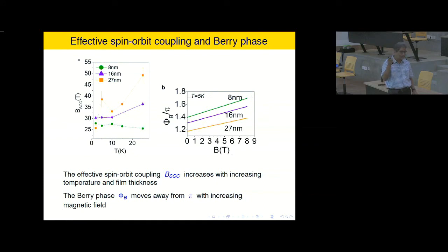Oh, the single crystal, by that I meant a really big crystal, a very, very thick crystal. If you take a very thick single crystal of bismuth selenide, then the surface state penetration depth is 0.8 nanometer. Now in this system, the grain size is typically the thickness. Here the thickness is about 2 to 3 nanometers per grain. And then we are assuming that the two separate grains almost touch each other, so there is not much distance between two grains.